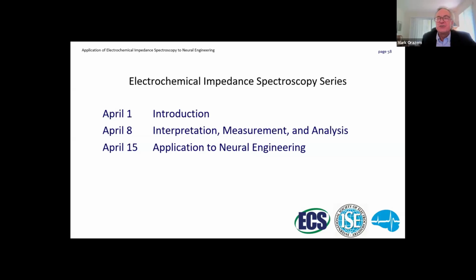There are other approaches that I have used. I will say they're not as well developed, but this may be food for thought. At the very beginning, when I talked about model development, I said that we're assuming that we can consider the charging current and the Faradaic current to be uncoupled, and then we build a model for the charging current separately from the model for the Faradaic current. That's not completely true. What we found was when we accounted for the coupling between the Faradaic and charging current, we saw a depressed semicircle very similar to what we see with constant phase element behavior.